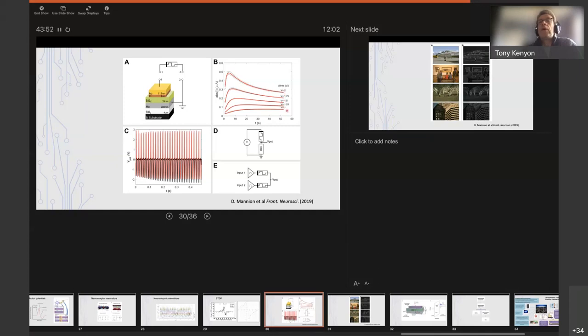So we go from 1 volt here, minus 1 volt, in fact, where we just see an increase in the saturation, to above maybe minus 1.5 volts, certainly evident at minus 2 volts, we see an increase and then a decrease. So depending on where we are, either side of this peak, we can either increase or decrease the conductance of our device by applying a bias. So we can exploit that by, instead of applying a constant bias, applying a series of pulses. And as the frequency of those pulses varies, we can either increase or decrease the conductance. And we can start to do computation with that.